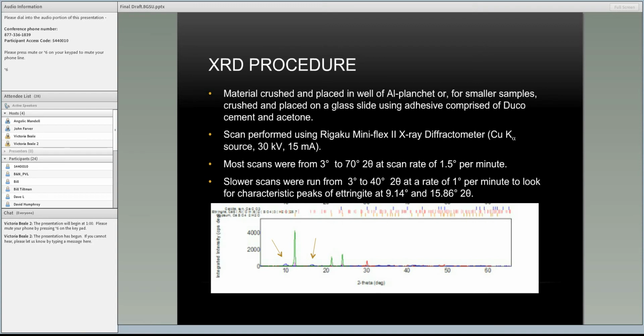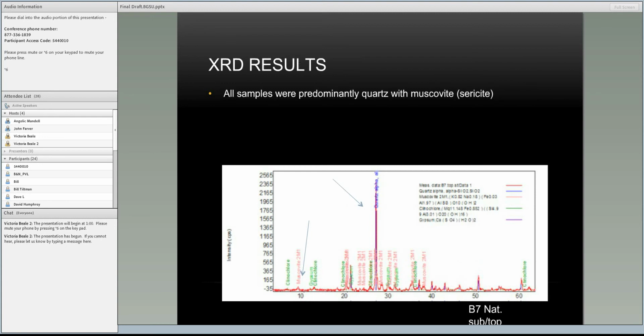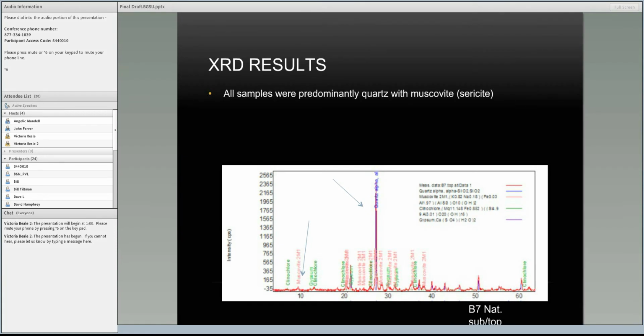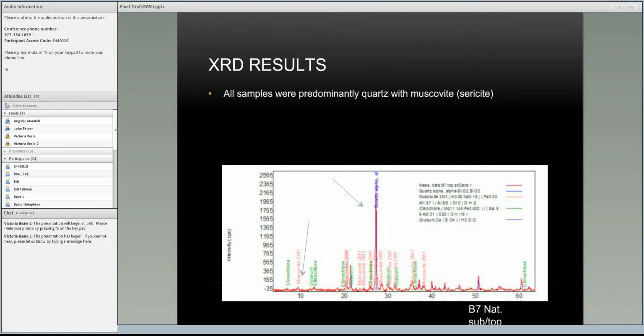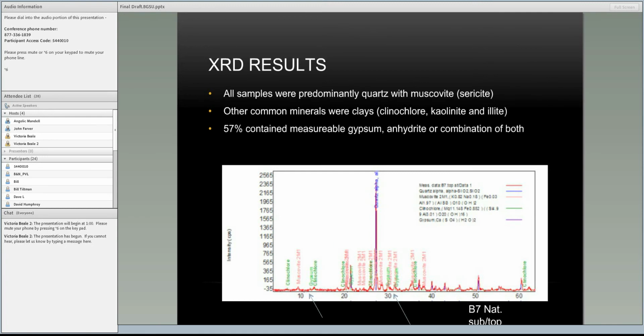Okay. With the boring samples that we looked at, all the samples were predominantly quartz with muscovite. It's kind of hard to see with that scan there, but the largest peak there is quartz, and the smaller peaks down at the bottom with the red lettering, that's the muscovite. There's also some clinochlore in there. And then the other common minerals were clays. There were a lot of clays in there: clinochlore, kaolinite, and illite. 57% of the boring samples contained measurable gypsum, anhydrite, or a combination of both.